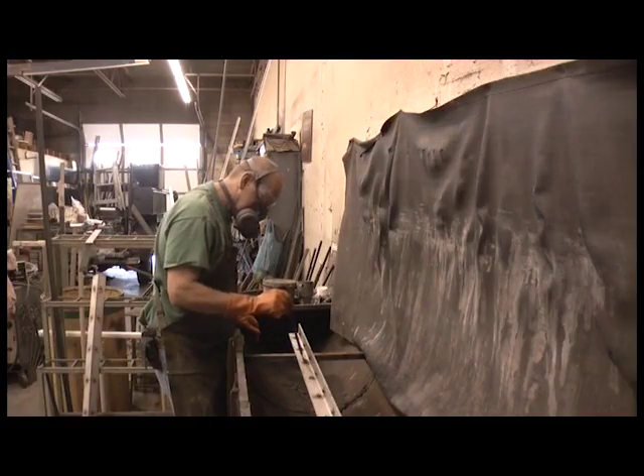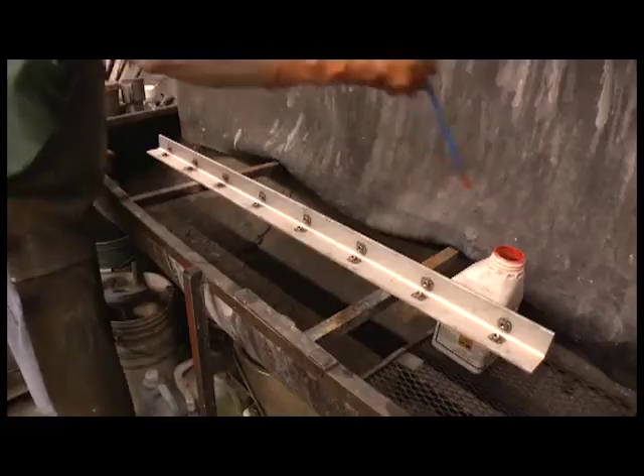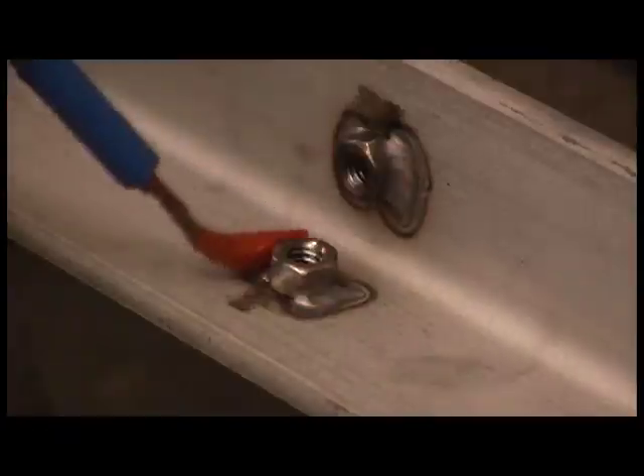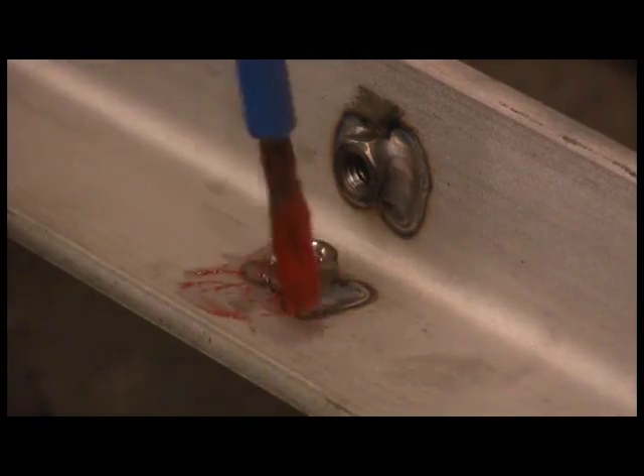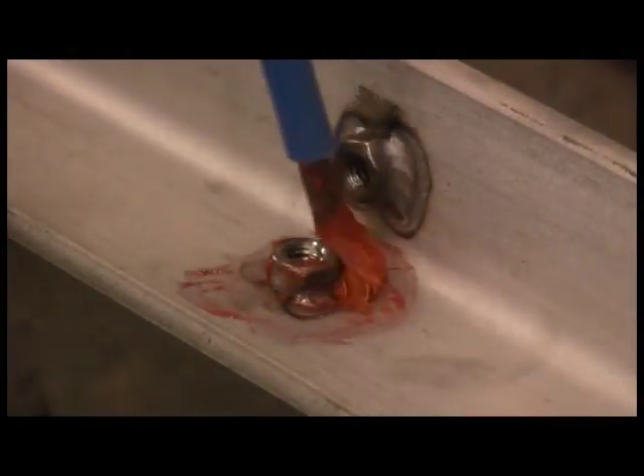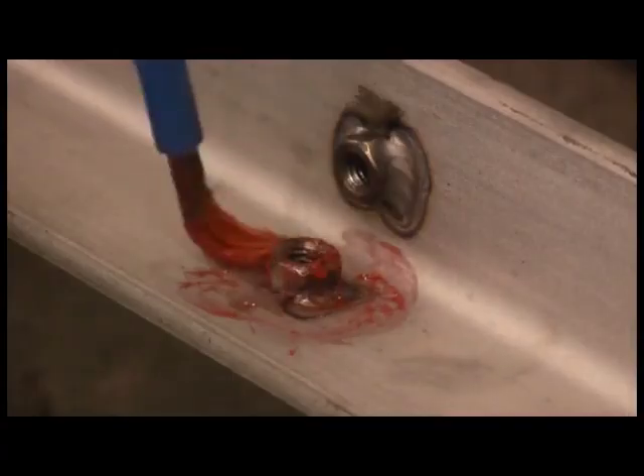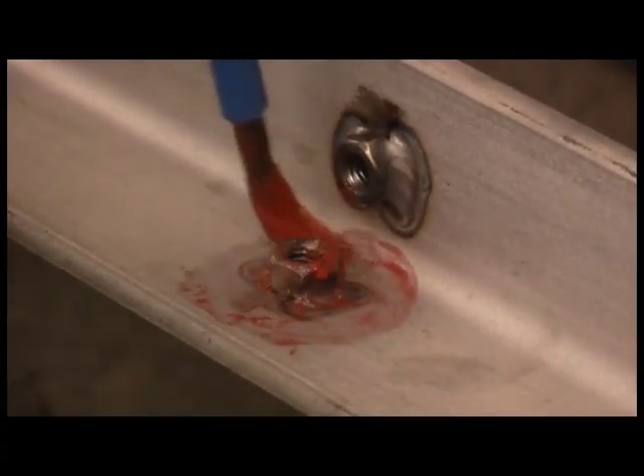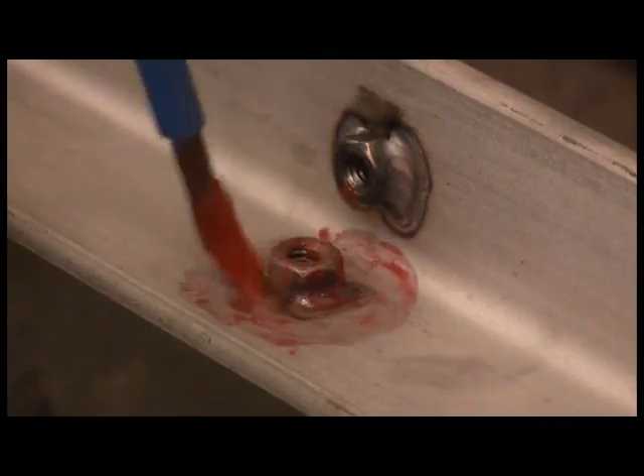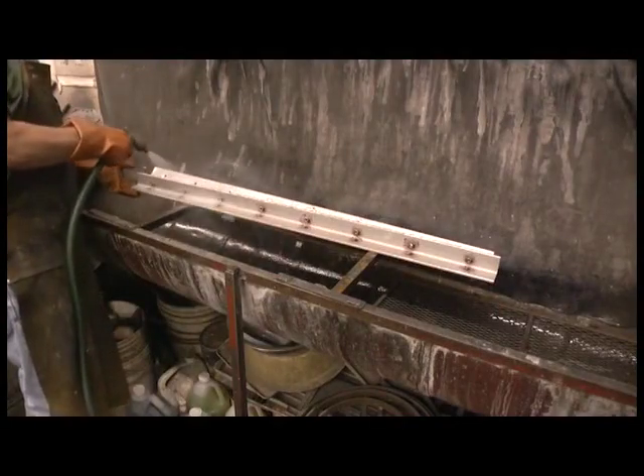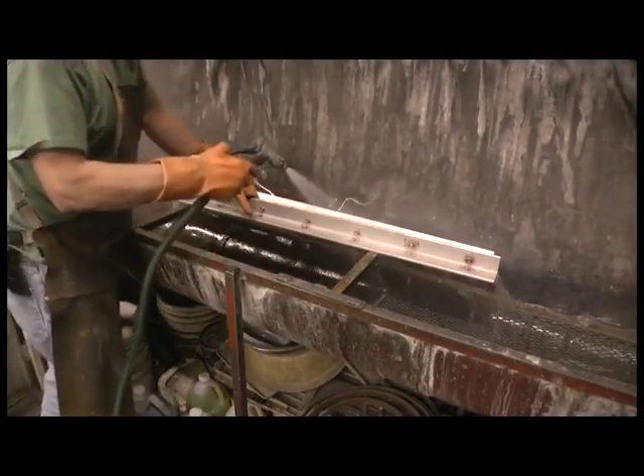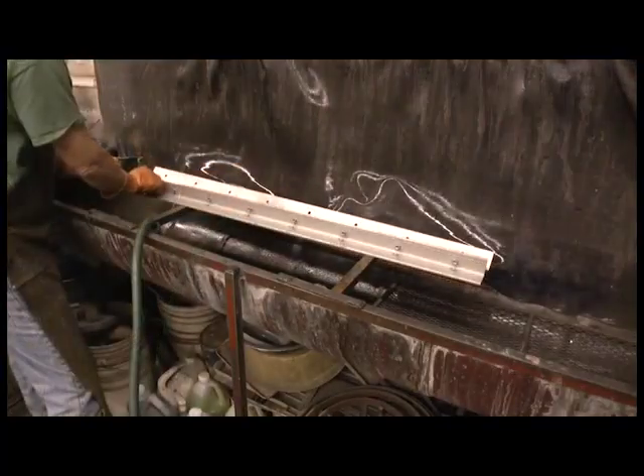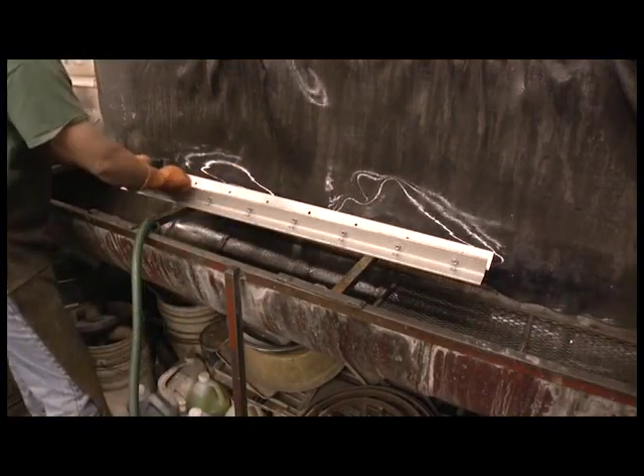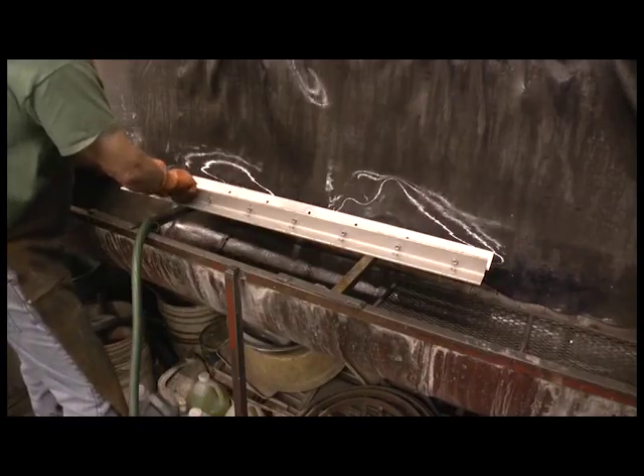The pickling compound also removed the colorful heat tint, which is an oxide layer and chromium depleted zone from the nuts welded on the uprights. After a suitable amount of time, typically an hour, the pickling compound is removed by rinsing and scrubbing the area of application.